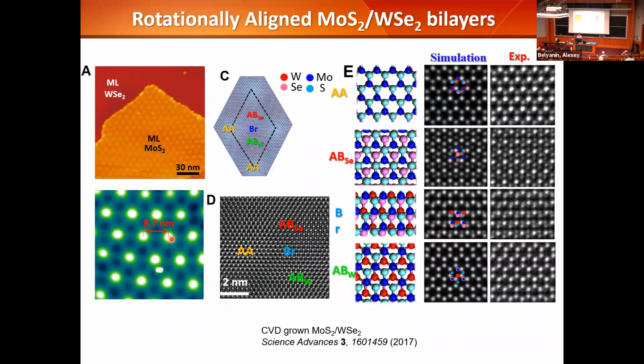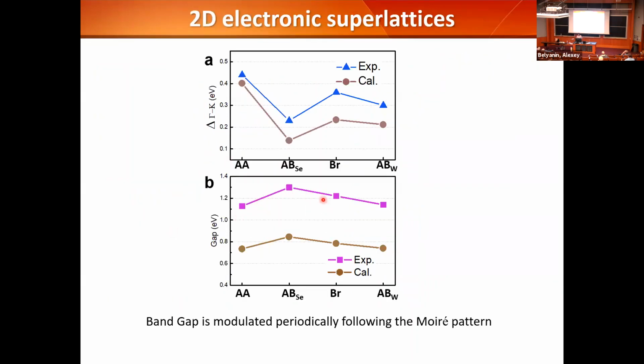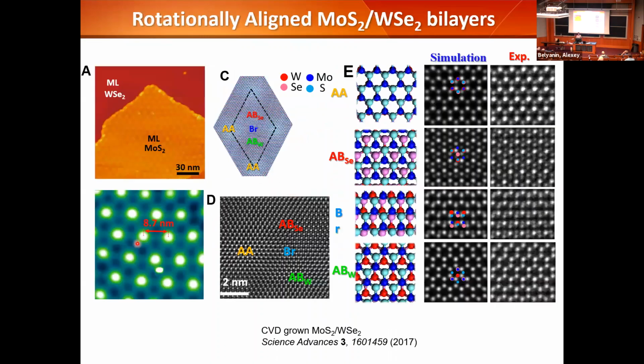And this is scalable. I can build many of these sites by simply making the layer bigger. This is a measurement. This is the measured band gap at several high symmetry points. As you can see, the band gap locally changes by more than 200 meV. So I have this periodic checkerboard pattern, and there are preferred energy traps where electrons or holes or excitons would like to sit. That makes them a really interesting quantum material that defines individual quantum systems, single electron, single hole, or single electron-hole pair, and puts them in a predefined position. So this is what makes them really attractive.